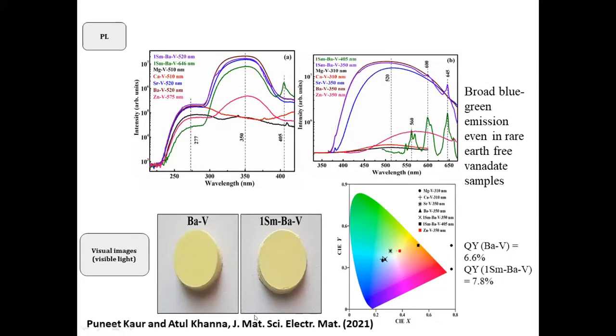So these are the visual images of the barium vanadate and samarium barium vanadate samples under ordinary light, your daylight, and we see this greenish tinge under visible light of a room. But if you expose it to a UV lamp of wavelength, say 250 nanometers or 350 nanometers, you see very strong green light emission. And their quantum yield values are in the range of 6 to 8%.